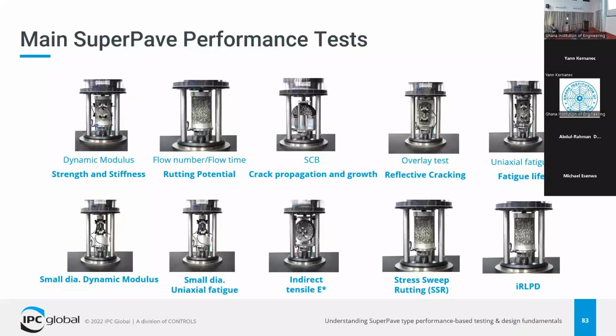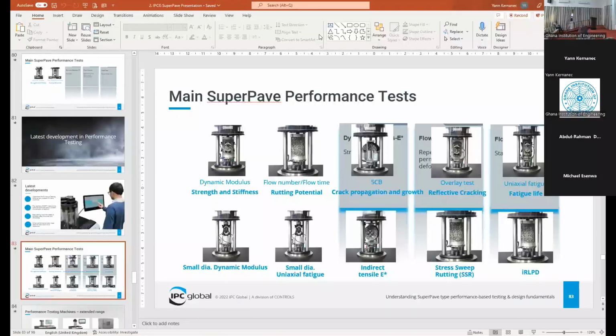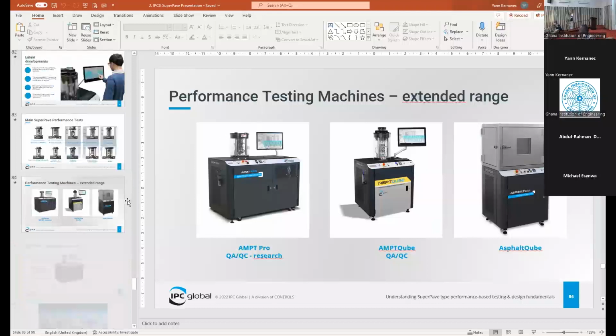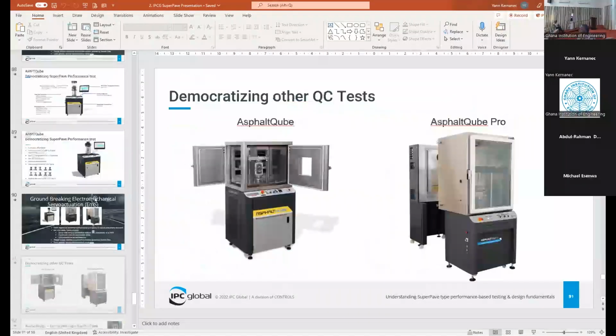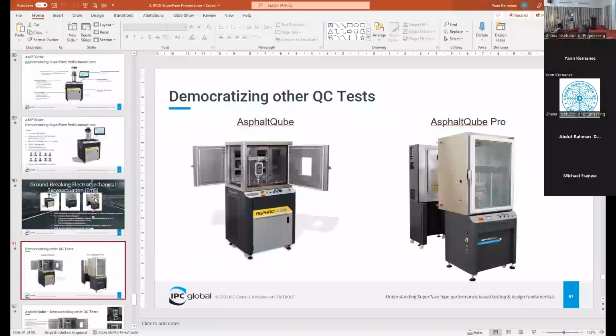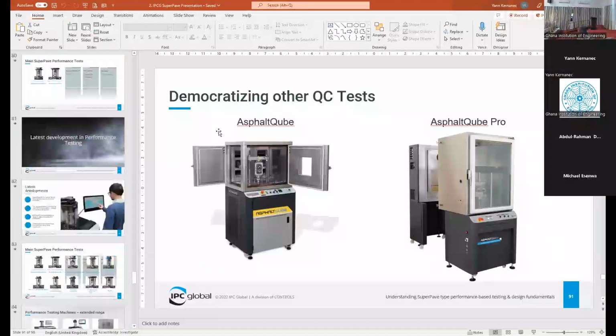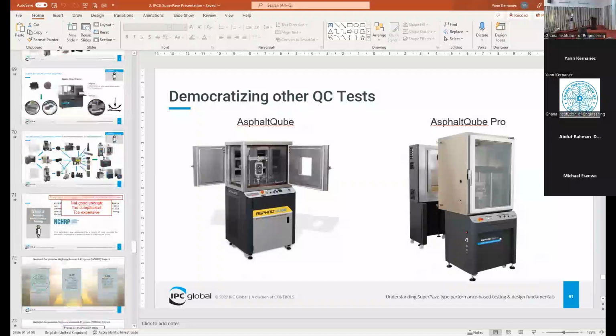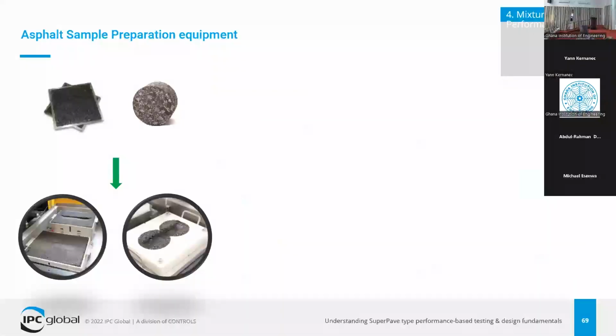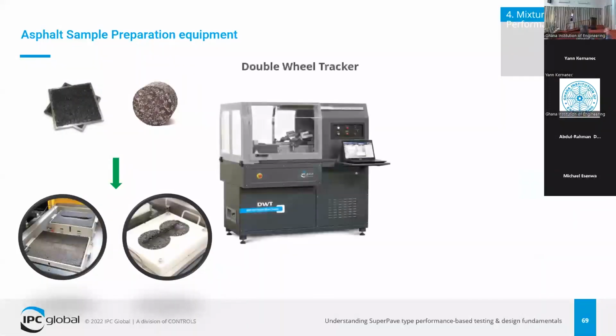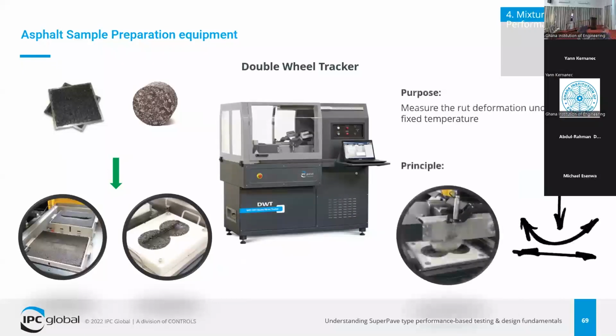If your temperature is 58 degrees Celsius, considering the binder high temperature that you have, if it is 64 minus 28, you can subject the heat of the water to 58 or 64 degrees Celsius and submerge that pavement sample while you run your wheel tracker test. So that will give you an idea how that pavement will behave in terms of flooding. If the pavement is flooded during high summertime, how it will perform under stress and loading. So yeah, this is the wheel tracker.